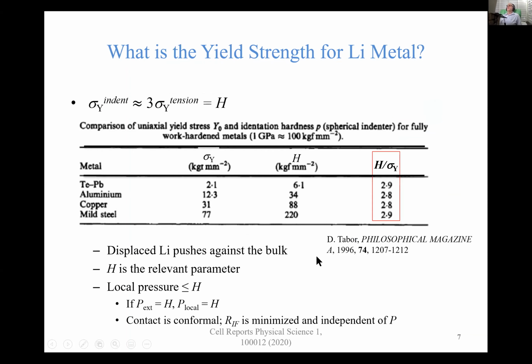So I mentioned yield strength, and in my work, yield strength is a critical parameter. There's a couple of different kinds of yield strength you can think about. One is the yield strength in tension. Another is the indentation yield strength, which tends to be about 3 times higher, and it's called the hardness. It's higher because in order to make lithium go plastic during indentation, the displaced lithiums have to push against the bulk, so you need to push harder.